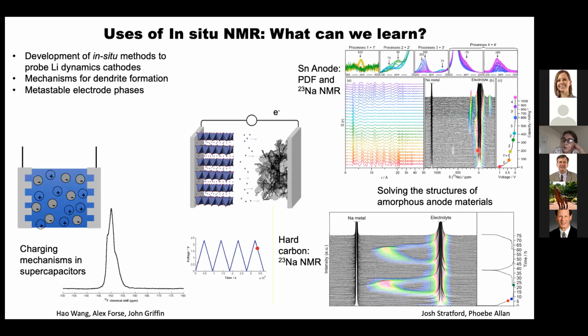And so it's of use to work out what's going on, so we can optimize this chemistry. And what we're doing here is, again, using the sodium NMR signatures to unpick and solve all the intermetallics that are formed when sodium reacts with tin. And then we can combine this with a technique, pair distribution function analysis, which is simply a total scattering method where you take a normal Bragg diffraction pattern, except you measure everything, so the diffuse and the Bragg scattering, and then you do a Fourier transform and bring it into real space, and each of those peaks tells you something about the pairwise correlations in the sample.